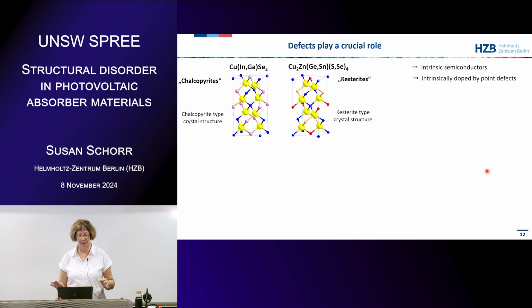So we have seen that defects are really crucial for semiconductors. You all know this from silicon. Silicon in principle is not conducting unless you have doped it. You have to dope silicon with phosphorus or boron to make it P or N type. With these compound semiconductors shown here, the chalcopyrites, copper indium gallium selenide or sulfide, or the kesterites, which is CZTS, so copper zinc tin sulfide or selenide, or sometimes mixed with germanium, they are so-called intrinsic semiconductors. That means they are intrinsically doped by their point defects.